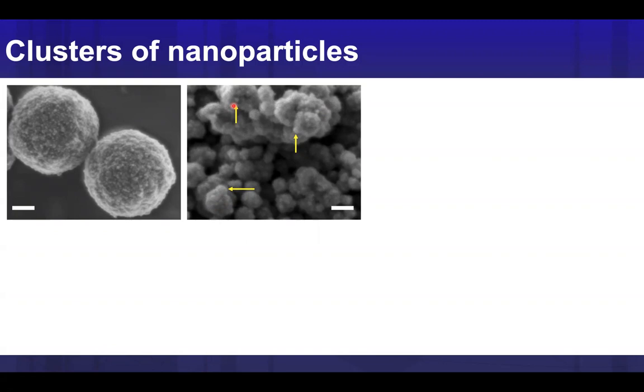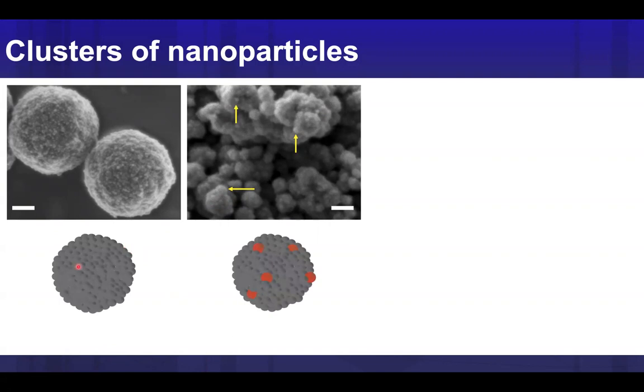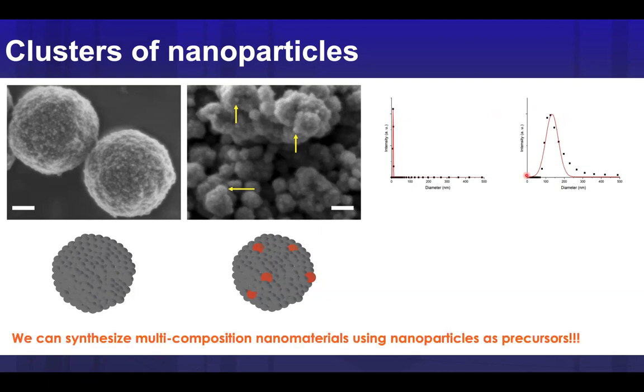Why? Because those are nanoparticles that we added. And the idea is that without the nanoparticles, we will be forming these. If we added them, we can put the nanoparticles inside of the cluster. And we corroborate this by DLS. We added our precursor nanoparticles, then we generate the cluster, and the nanoparticles are not free anymore. And this is very exciting because now I can change the composition of these particles, and I'm generating different materials, and the possibilities for applications are widely open, right?